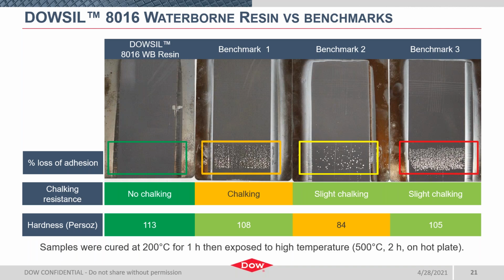If we look at hardness first, although this isn't always a definitive test to indicate performance, I know I've formulated high temp coatings with pendulum hardnesses ranging from 80 all the way to 140. There is one obvious outlier here, and that's that second benchmark product showing a significantly lower hardness. We also didn't see material loss with the tape adhesion test in the 8016 formulation, whereas all the other competitive products show some material removal, and in the sample on the right, a quite severe material loss.